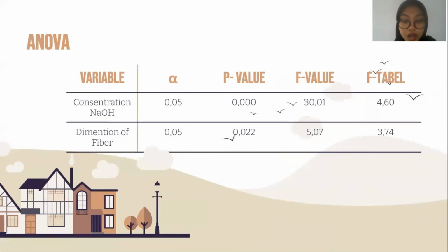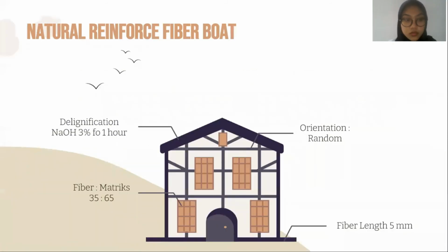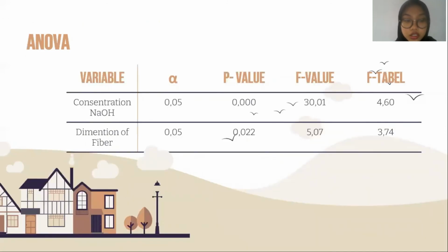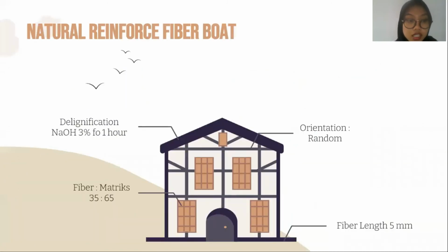Next is the result of ANOVA. On the concentration and fiber dimension variables, the p-value is smaller than alpha and the F count is bigger than the F table. According to the ANOVA result, there is a rejection of H0 in both independent variables. So it can be concluded that the concentration of natrium hydroxide and length of fiber affect the tensile strength. Next is the result of NRFB. The natrium hydroxide concentration used in NRFB fabrication is 3% with a fiber length of 5 millimeters.